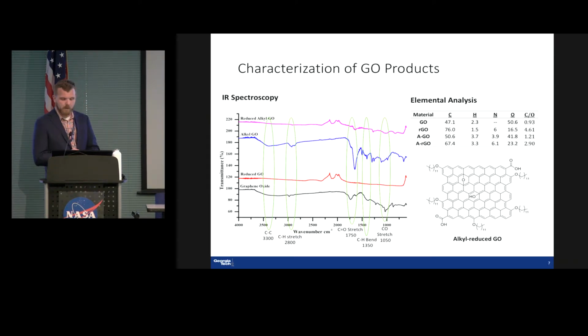Specifically, what I want to draw your attention to on the left here is the IR spectrogram of the various products that I've discussed so far. If we look at the CH stretch, we'll see that in graphene oxide we get a nice little bump here. See if I can do this with this little pointer. But yeah, graphene oxide, we've got this nice little bump, and then when we reduce it, we get rid of all of that. And that is the change from sp3 carbon to sp2, highly planarized, and so we eliminate that